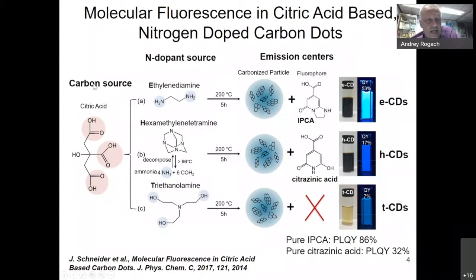So what we did here, again, we took one and the same carbon source, which is citric acid, and then we took 3 different amines. And depending on the amine, we ran the reaction at one and the same condition, 200 degrees centigrade, 5 hours. This is a very classical kind of synthesis to carbonize those precursors. Then we get these dark solutions, and they did contain carbon particles all the time. So we saw them in TEM. But on top of these carbonized particles, they also contain molecular fluorophores.